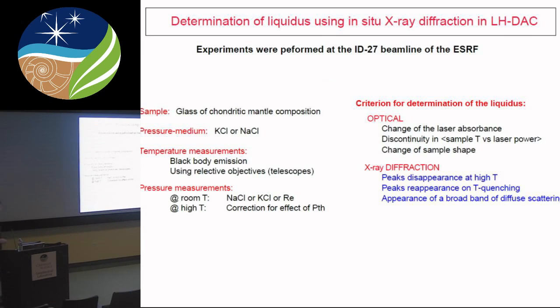So what we do now is we use, for a long time already, a diffraction beamline. For diamond cell experiments, we now start almost exclusively with glass as a starting material. Glass that we prepare using the levitation method, because on a level of 10, 20 micron of the laser spot and a couple microns of the diffraction spot, we want homogeneity. Homogeneity is only achieved when we do the glasses. It can be chondritic. Our chondritic is not far from pyrolytic type mantle.